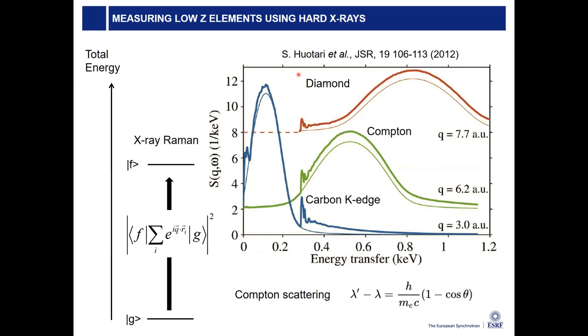This is well known. And what is nice is that you see here something like an absorption edge. So in this case, Simo scattered 10 keV photons from a diamond sample and changed the scattering angle. And that changes the Q. The Compton peak moves around, but this line here does not change. It stays at a fixed energy transfer. So it's an energy that is transferred from the 10,000 electron volt incoming beam. It transfers roughly 300 electron volts to the sample. And at this 300 electron volts, I see an absorption edge. I see the carbon K edge that I usually can only observe using soft X-rays. So I could do absorption spectroscopy at the carbon K edge directly at 300 electron volts.